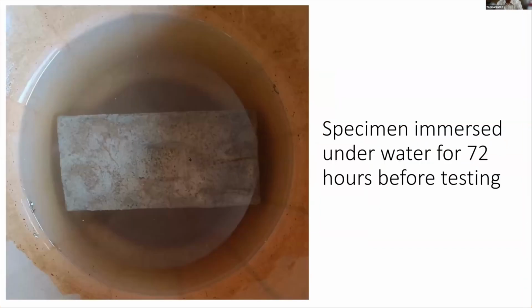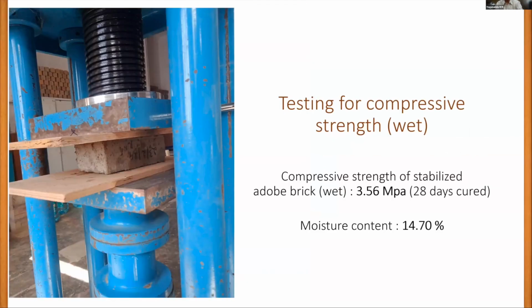Then what do we do later? We need to look at what is the strength of the brick. That is wet strength of the brick. The process of understanding the wet strength is to immerse that brick in water for 72 hours, that is 3 days, and then take it to a testing machine and load it to failure. So that is expressed as MPa, megapascals, or newtons per millimeter square.